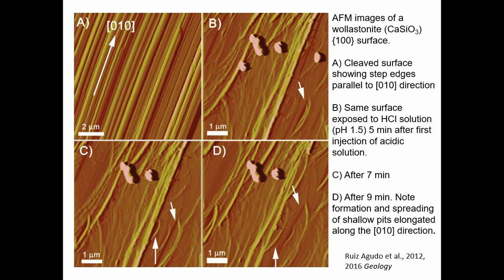We took wollastonite, a very simple silicate, because we're wanting to look at a whole range of minerals to see if this process is holding. And so you can see A is the dissolving surface of the wollastonite. Once the solution goes on the surface, then B, C, and D show a progression, a time sequence of the formation of the nanoparticles which are merging on the surface, and that new phase is silica. So this is what's called the leached layers during chemical weathering of silicate minerals.